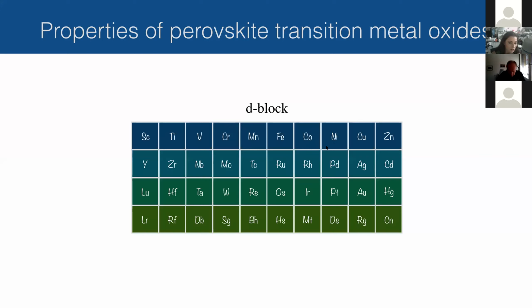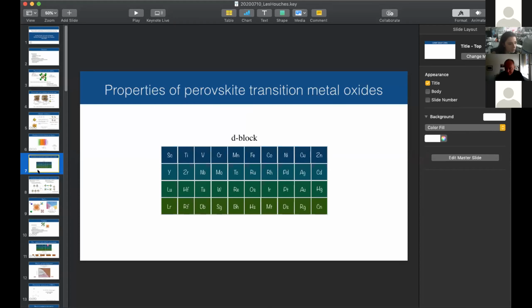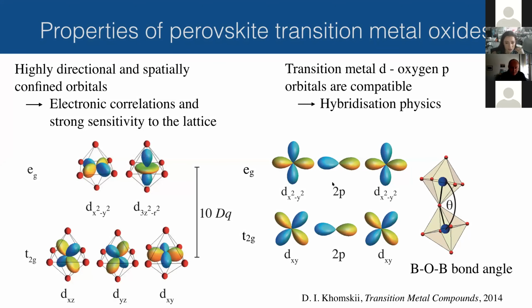It's actually not super similar because this one is T2G, so its orbitals are completely different from nickel, which is EG. If you look at the next slide, you see that the T2G orbitals actually don't line up with the oxygen 2p, whereas the EG orbitals do. One thing that comes out of this, and this is general to the right side of the transition metal block, is that in the nickelates you have quite easily hybridization and charge transfer between the nickel and the oxygen, whereas in the titanates, and lanthanum titanate is not an exception, you have not so much interaction between the titanium and the oxygen. For the nickelates, this nickel-oxygen hybridization is super important for the physics. So you can't really compare it to the titanates in the same way.